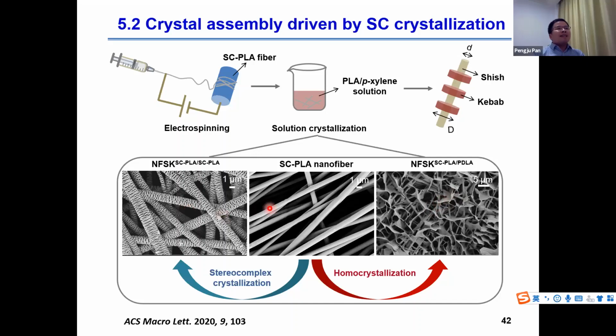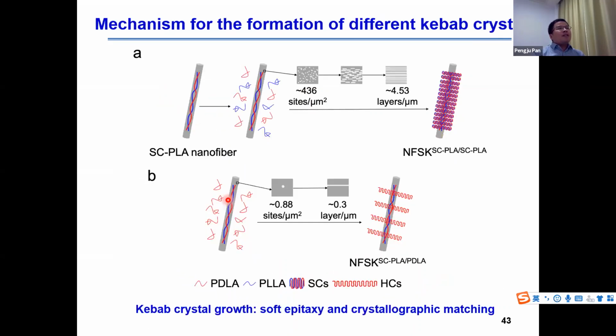In the case of the homopolymer solution, the growth of the kebab is homocrystallization. We get very big kebab crystals with loose packing. However, in the case of the PLLA, PDLA mixed solution, the growth of the kebab is stereocomplex crystallization. We get very small kebab crystals with tight packing. The different morphology is related to the nucleation mechanism of stereocomplex and homocrystallization on the stereocomplex fiber.